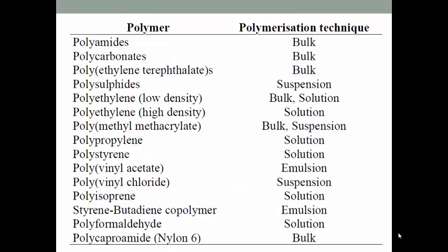Actually, emulsion polymerization is totally different from bulk polymerization and suspension polymerization used in other radical polymerization. In this case, the radical responsible for the polymerization is only one in a micelle, and the polymerization does not stop until the next radical enters a micelle from the water phase. Moreover, if the monomer in the micelle is consumed, monomer will be replenished from the monomer droplets in the water and polymerization will continue.